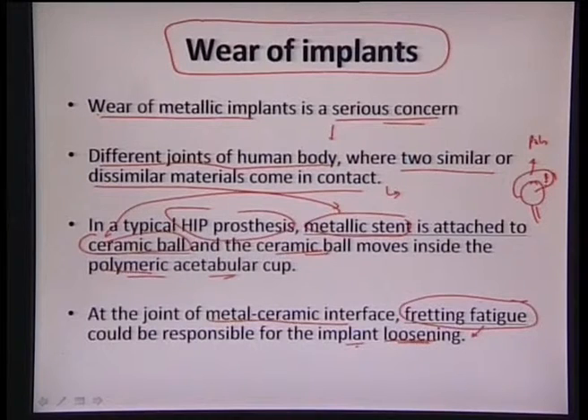So if there is wear happening between the metal and ceramic interface, that will tend to increase the gap between the two. Once debris is released, or a gap is generated, obviously it will lead to loosening of the implant, and we'll need a resurgery to put the implant back into the body and basically do one more surgery. So that particular material has failed because of poor wear resistance. That is the highly critical part in terms of increasing its mechanical properties and improving its wear resistance.